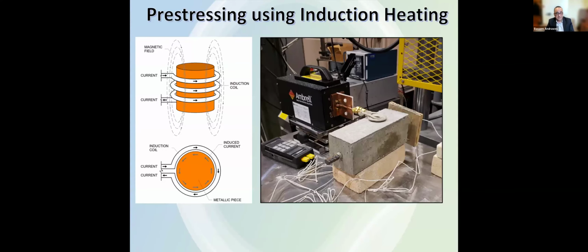And we thought about induction heating. Some of you might be familiar with this technology. The idea is very simple. You have this coil that generates an electromagnetic field. And if a magnetic metal happens to exist in that field, then it will actually run a current in it, and that will heat up the material. So we're able, for example, just by scanning the top surface of this concrete block, to heat the bar inside and make it reach about 200 or 300 even degrees Celsius in a matter of few minutes. So that was an exciting technology that we wanted to explore in TRANS-IPIC.